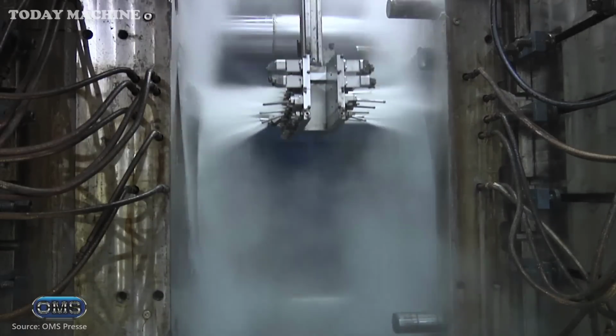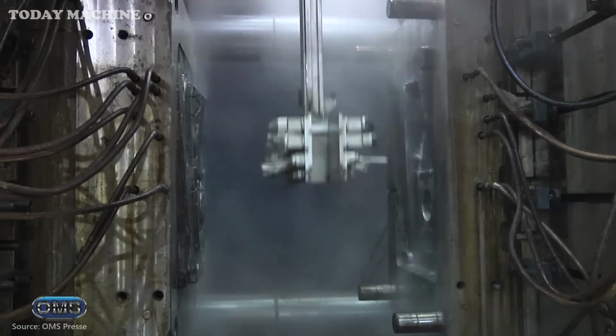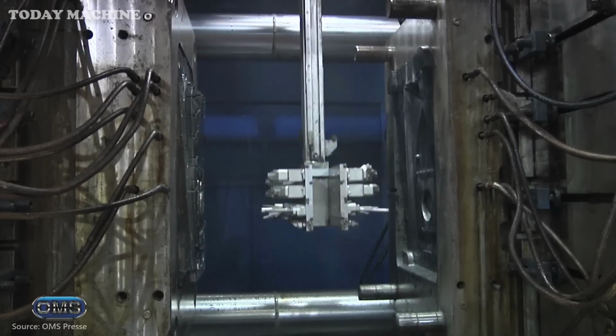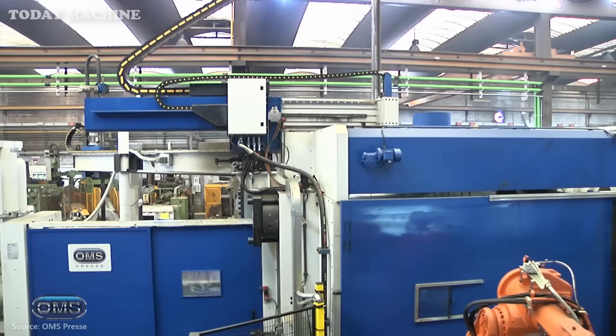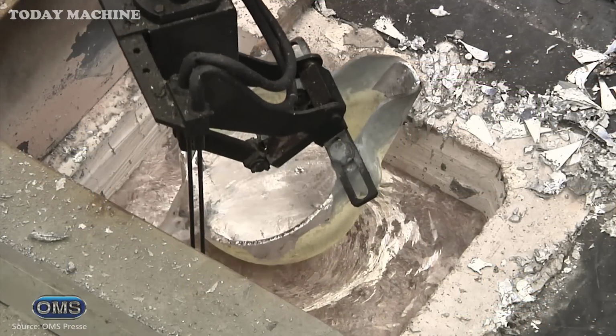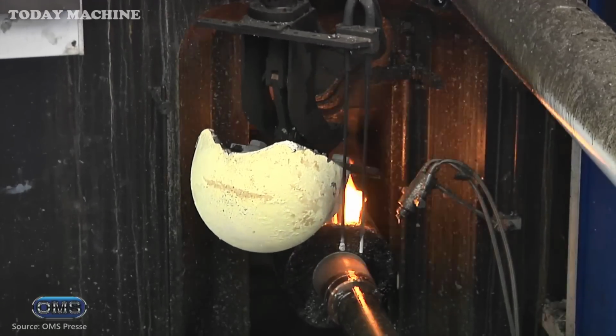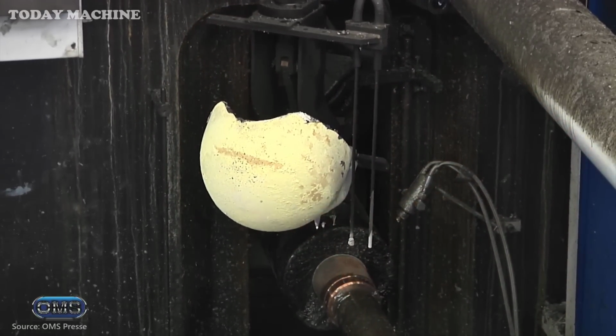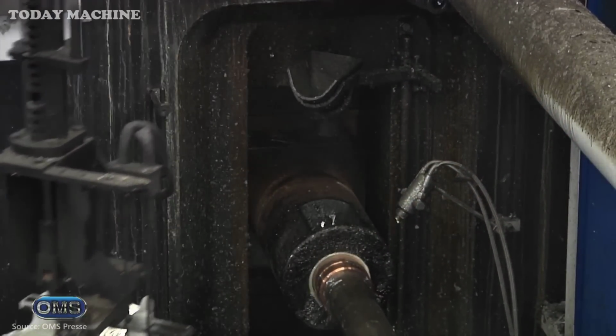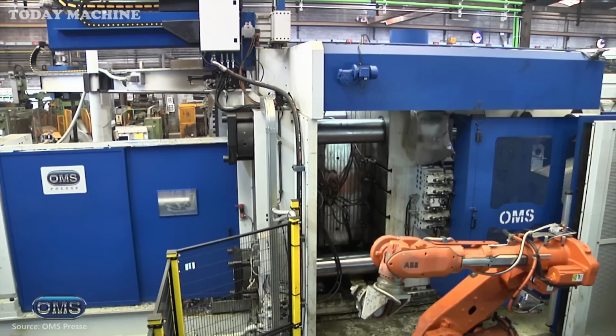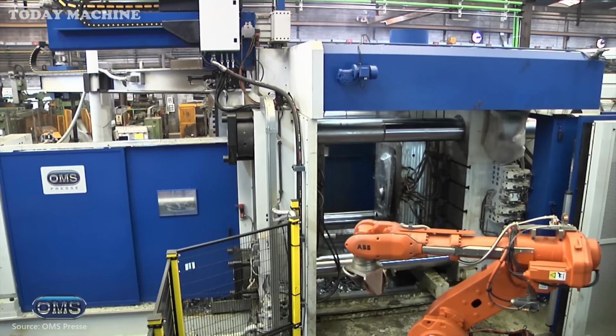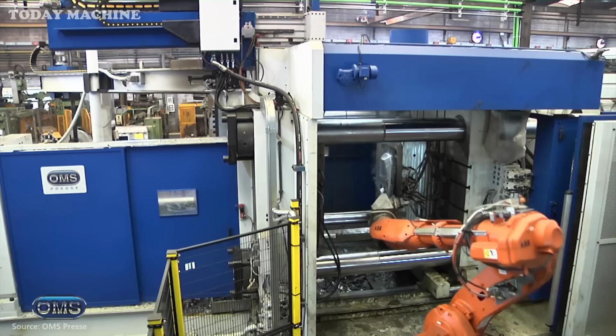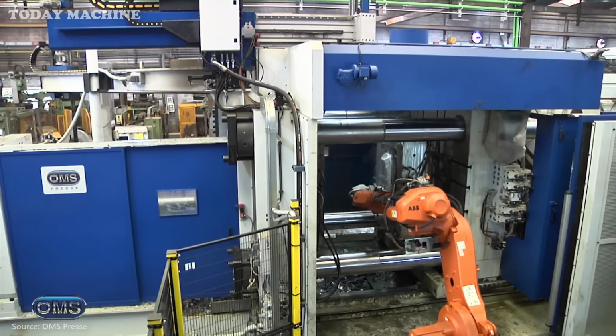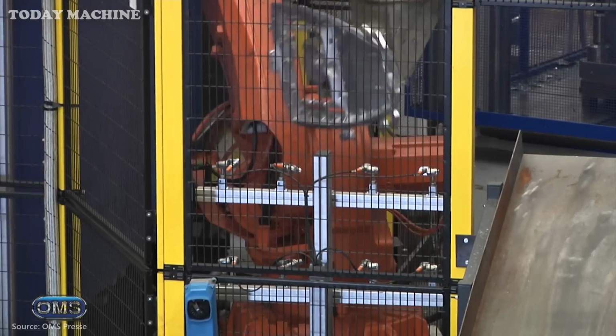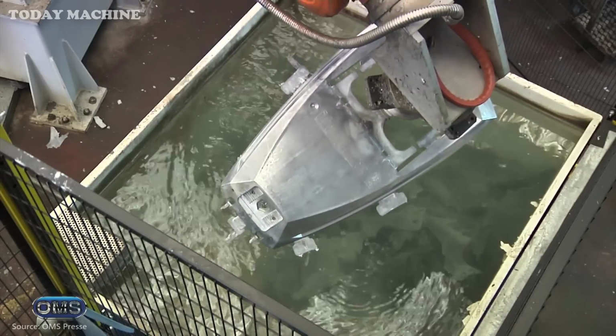Once the metal is in the chamber, a hydraulic piston rapidly injects it into a steel die under high pressure, ranging from 350 to 3,500 tons depending on the machine model. The high pressure ensures that the molten metal fills every cavity of the die, creating detailed and consistent shapes. After cooling and solidifying, the die opens and the finished part is ejected.